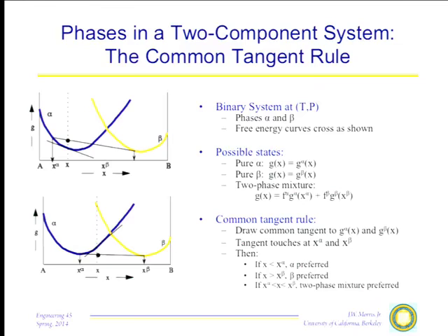If it were in a mixture of two phases, alpha and beta, then let's take a possible composition for the alpha phase and a possible composition for the beta phase and find out what the free energy of the aggregate would be. If we adjust the amounts of alpha and beta so that the total concentration is right here, I won't do the math, I'll just tell you the answer: if I take a straight line that connects the hypothetical concentration of alpha to the hypothetical concentration of beta, then the free energy of the mixture will be right here, where that straight line cuts through the vertical dotted line at the composition x. That simple graphical construction, which you can prove mathematically, and it's proven in the notes, will give you the free energy of any possible combination of alpha and beta.